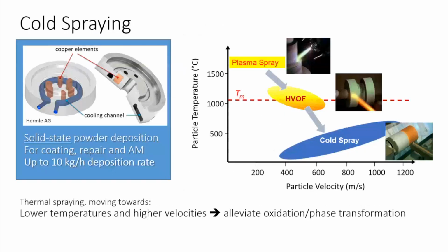Cold spraying, for some of you, might be already a familiar topic, but for those of you who don't know anything about cold spray, this is basically a powder deposition method. Like any other thermal spraying method, you use powder and then you accelerate the powder particles and deposit them on a substrate to build coatings. And that's used nowadays also for additive manufacturing. The main difference between conventional thermal spraying processes is that the particles of the powder remain in the solid state. So it's basically a solid state deposition process. Why? Because if you manage to reduce the processing temperature, you avoid oxidation and you avoid undesirable phase transformation. That's the main motivation behind the development of cold spray.